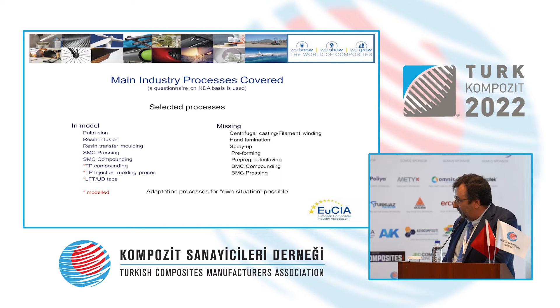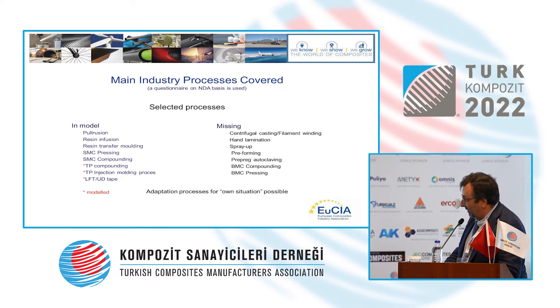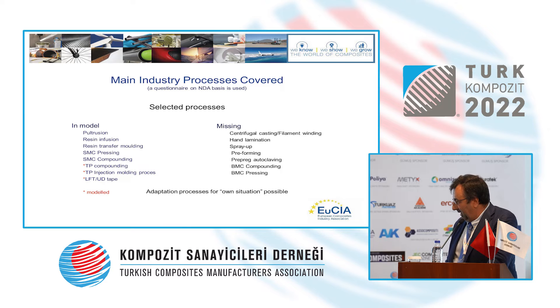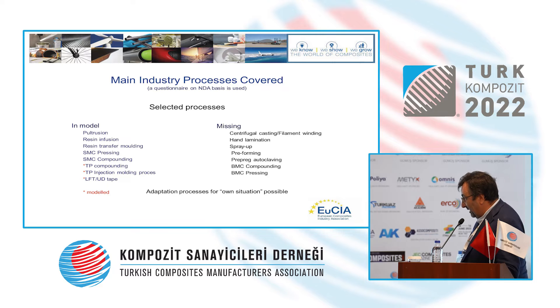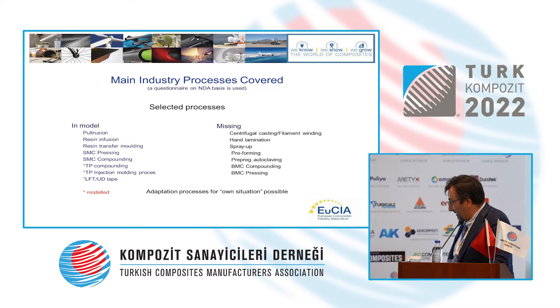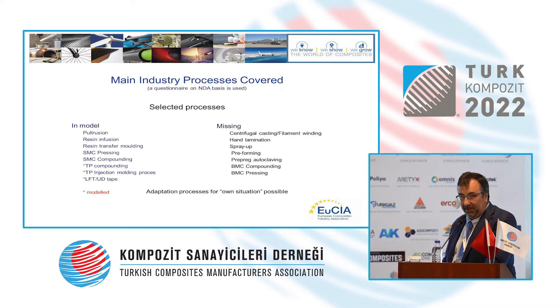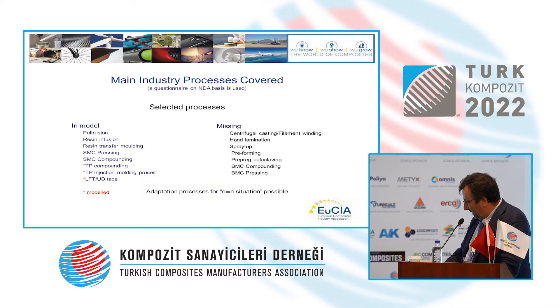Selected processes available in the model include pultrusion, resin infusion, resin transfer molding, SMC processing/molding/compounding, thermoplastic compounding, injection molding, and long fiber technology for unidirectional tapes. What is currently missing from the tool is hand lamination, spray-up, autoclaving, and centrifugal casting, but work is underway to include those processes in the near future.